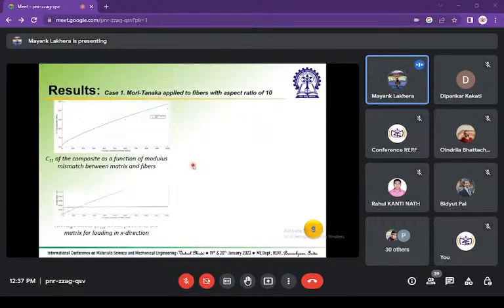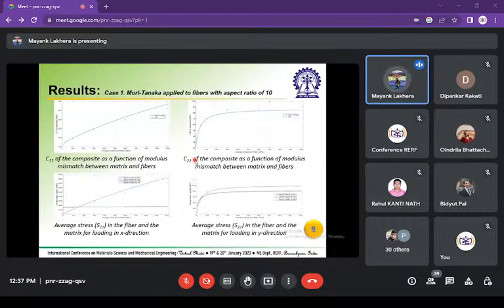So we can conclude from this that the FE results and Mori-Tanaka results match for lower aspect ratios. For aspect ratio of 10, which is higher aspect ratio, we can clearly see that there is a deviation when we go to a higher modulus mismatch. So this x-axis is basically Young's modulus of the fiber, and this is the C11 of the composite. Similarly, this axis is Young's modulus of the fiber.